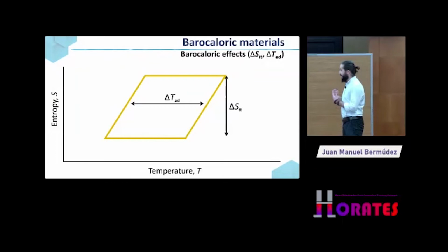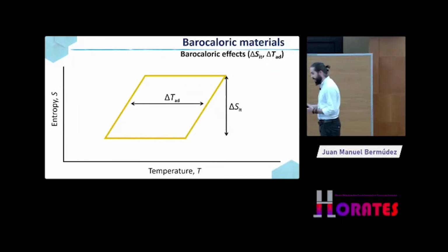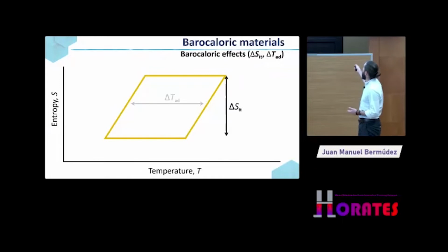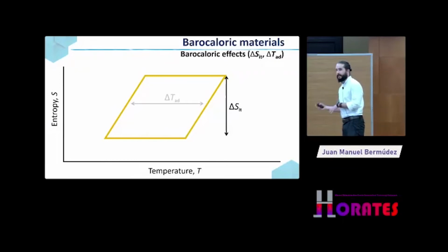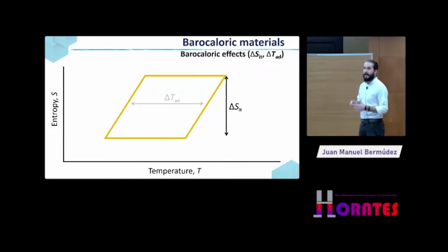But in the literature, most of the experimental studies have been focused over the years mainly on the isothermal entropy change, because the equipment that is in the lab can characterize better the heat flow of the material than the temperature change in adiabatic conditions. And for that reason, in this talk, I'm going to focus mainly on this isothermal entropy change. Those two parameters are also known as pressure-induced thermal changes or barocaloric effects. So when we talk about barocaloric effects, we have to distinguish between this one and this one. We have to identify which one we are talking about.